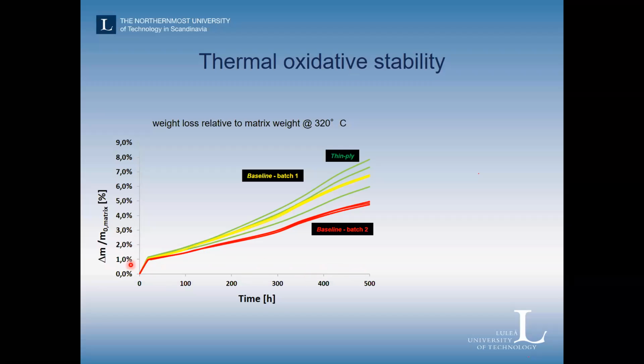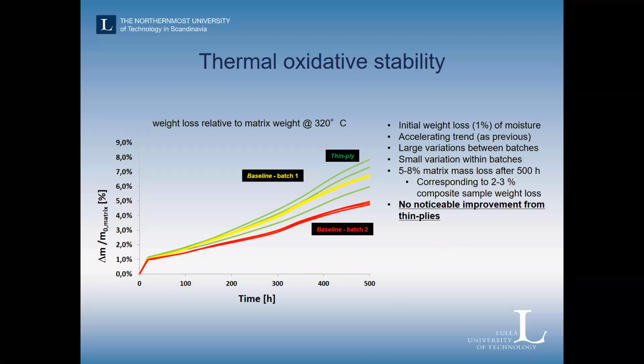So during the 500 hours, we notice an increase in the weight loss. The yellow one is for a baseline material, meaning the satin weave. The red one is also a baseline, the same but from a different manufacturing, and the green one is the thin ply. What we notice, first of all, we notice an initial loss here as well due to moisture loss in the very early stages of the test, and then we start to notice weight loss that increases. There is an accelerating trend. There's quite a big variation between the batches, but small variation within the batches.